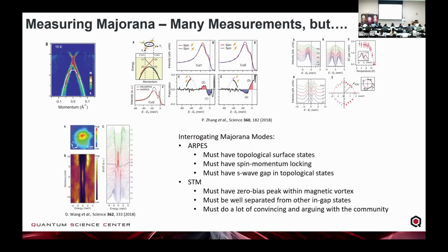Some of the complications here are how we interrogate it and how we confirm that this is indeed a topological superconductor. In our ARPES, there are certain things we would want to look for to see if it's even a candidate topological superconductor. It has to have surface states. We have to see the spin momentum locking, and you need to see this s-wave gap in the topological states. But this is complementary to the STM, where you have to see these zero bias peaks, because this is, again, sort of half an electron, half a hole. These Majorana modes are going to be a quasi-particle that lives at zero energy. But there are going to be a lot of other trivial states that might appear inside this superconducting gap.